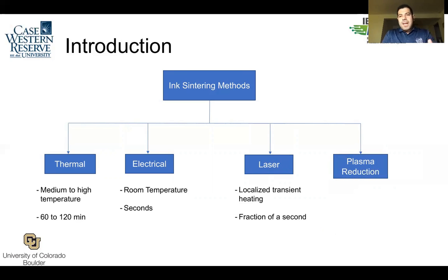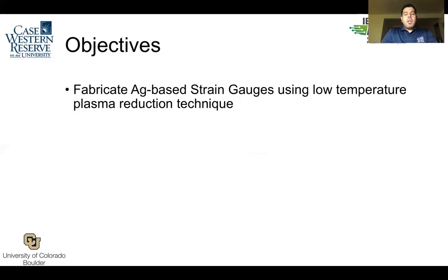The last one is plasma reduction. This is the ink sintering method that we use in our work. Plasma reduction is a low temperature, below 100 degrees Celsius, and it takes minutes. That's the introduction. Let's move on to the objective of our paper. The objective is to fabricate silver-based strain gauges using low temperature plasma reduction technique. And we're also going to investigate the effect of argon plasma reduction time on gauge factor.